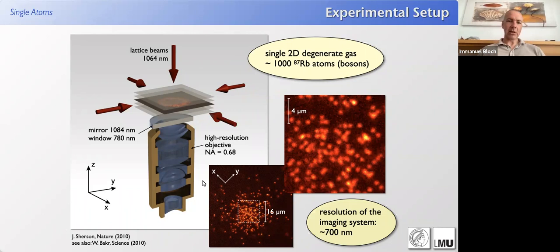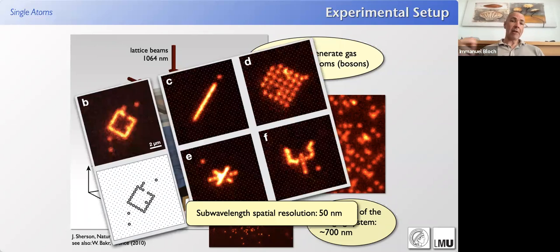And here you can see pictures of this single atom fluorescence images, where you can see in the image is actually a single atom in this lattice. So this is just a thermal state, so it's not a very interesting state, but we can really nicely see each individual atom in this system. We can also control individual atoms in the lattice by focusing a laser beam through this objective onto the atoms, and then we can move them around or rotate their spin states.